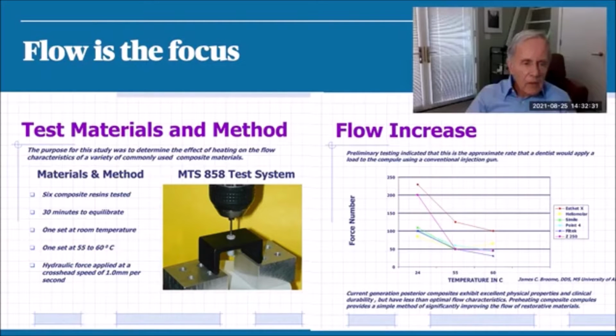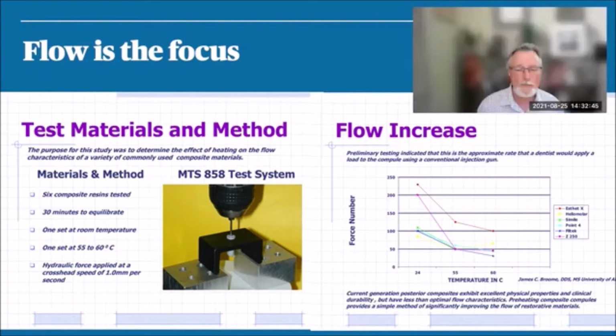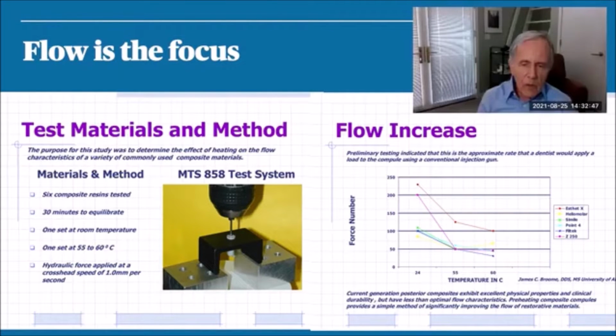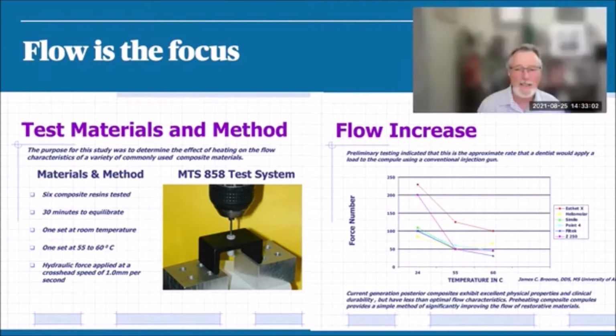Well, that's absolutely true, Larry. We'll see this in another slide, but basically what happens is when you use a flowable, yes, it does adapt better to the walls of the restoration and preparation. But what you also know is that flowables shrink much more than composites do. So what you're trying to do by creating a better adaptation, you're losing once you polymerize the material, because the material is going to shrink and you don't have that condition when you use warm composite. And we'll see this in the next slide. I appreciate that, Josh. Let's go there now.